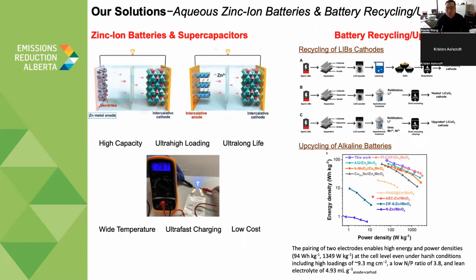And the second solution is the battery recycling I just mentioned. We mainly focus on two things. One is the recycling of lithium batteries. For example, the lithium cathode plays a key role and takes most of the cost of the batteries. So we try to recycle the lithium cathode materials and regenerate them in two ways. One is that we leach the materials, particularly recycling the lithium and the transition metals like cobalt and nickel, and then we precipitate them, and then we can make the lithium cathode materials again. Another way is that we regenerate them together by re-lithiation, and by adding some other additives, we can realize cathode materials with even higher performance than the original spent lithium cathodes.